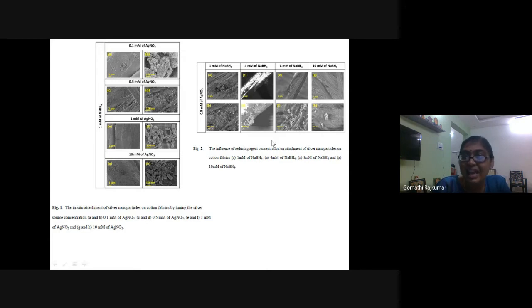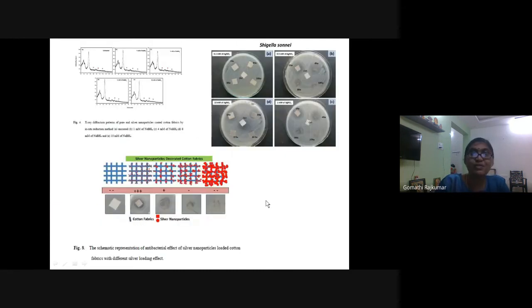And then here again we tested with the reducing agent, with varying concentrations of sodium tetrahydroborate. And again here you can see that there are differences in the size and the shape of the nanoparticles. So this was our first finding, which we confirmed. And here, I'm sorry, this is the X-ray diffraction studies that we used. So these are the antibacterial activity results. This cotton fabric was produced by this method.